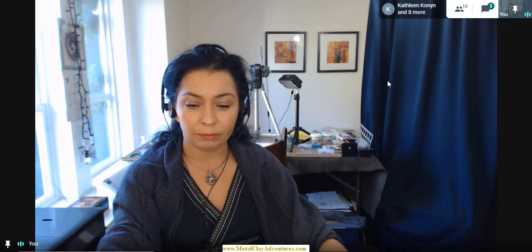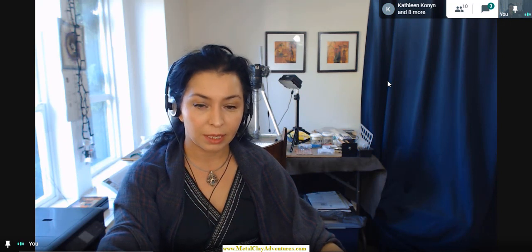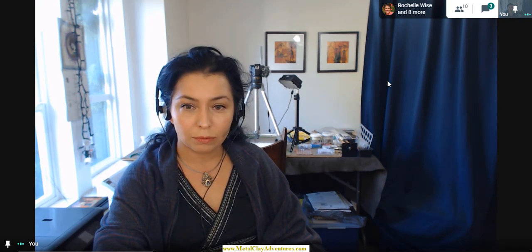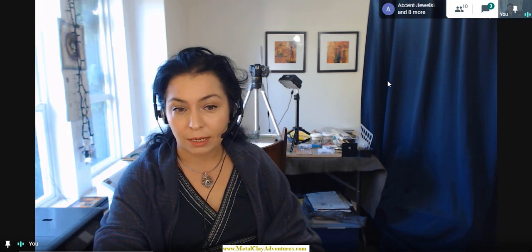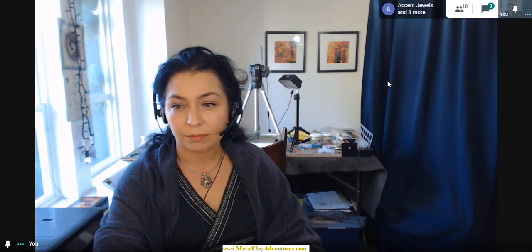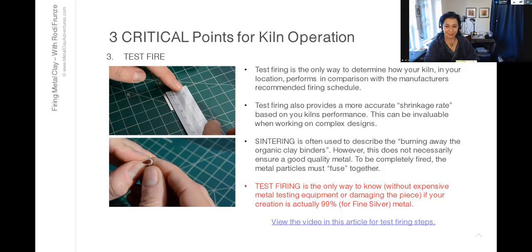If you got the kiln, I would recommend you to run it empty the first time and see if it holds the temperature and if it holds for the time you need to fire your metal clay. So let's say you want to fire fine silver, so run the kiln at 1650 for 2.5 hours and see how it holds the temperature. And second, you'll need to test fire metal clay itself. You cannot avoid and you cannot skip this